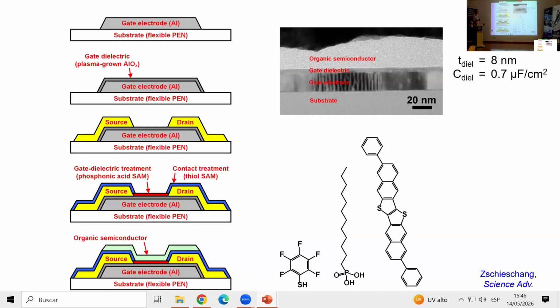So this is how we make the transistors. It's basically a 5-step process. It takes about 1 week. So we deposit the gate electrodes, pattern them by electron beam lithography. We use aluminum because that allows us to grow a very thin layer of aluminum oxide simply by plasma oxidation on the surface of the aluminum gate electrode. That is our gate dielectric. Has a thickness of about 8 nanometers.